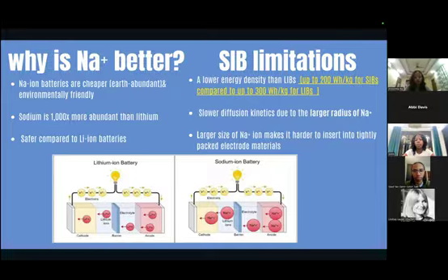Sodium-ion batteries also have some limitations. They have a lower energy density than LIBs, which is up to 200 watt-hour per kg for SIBs compared to up to 300 watt-hour per kg for LIBs. And they also have slower diffusion kinetics due to the larger radius of sodium ions. And lastly, the larger size of the sodium ion makes it harder to insert into tightly packed electrode materials, reducing diffusion speed and structural stability.